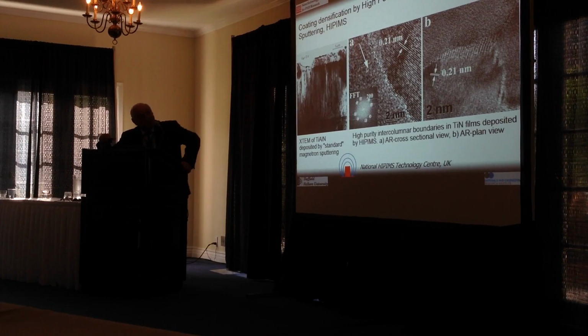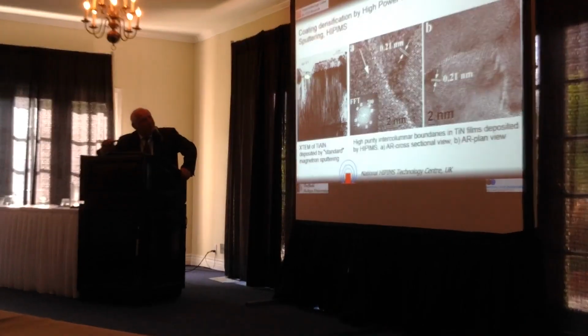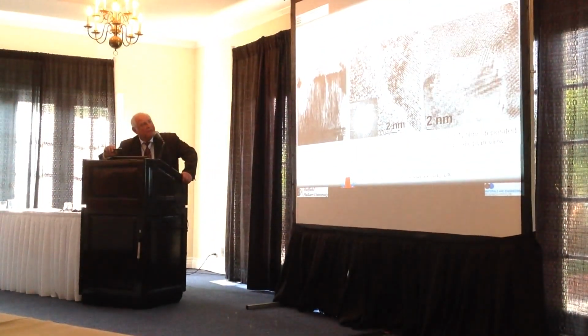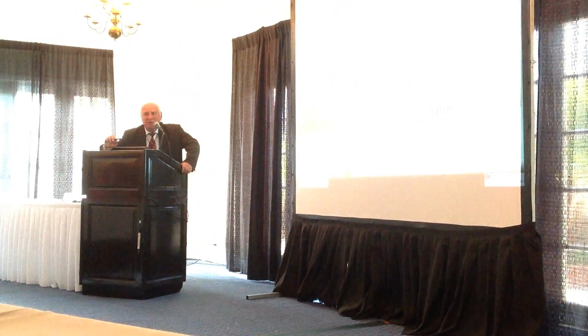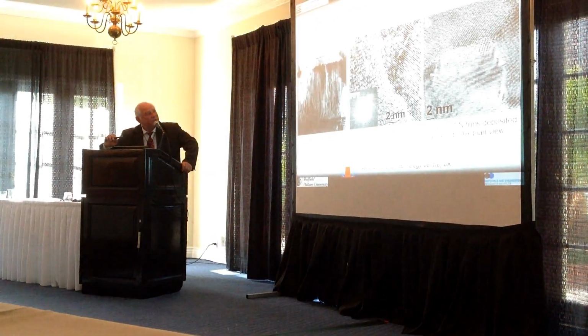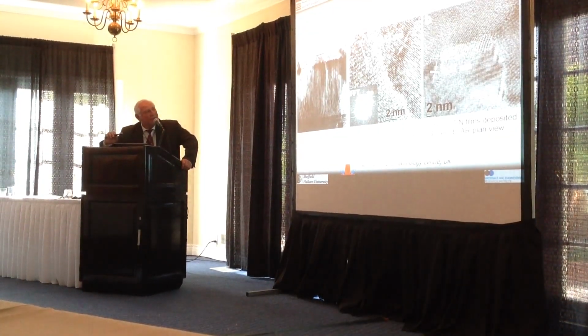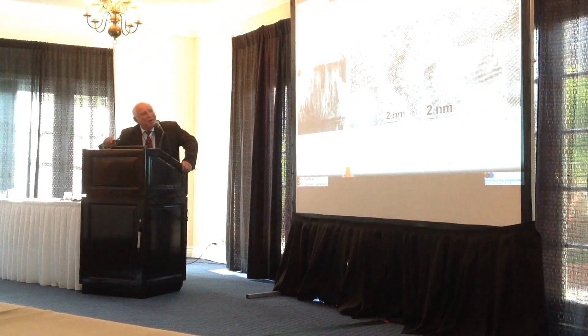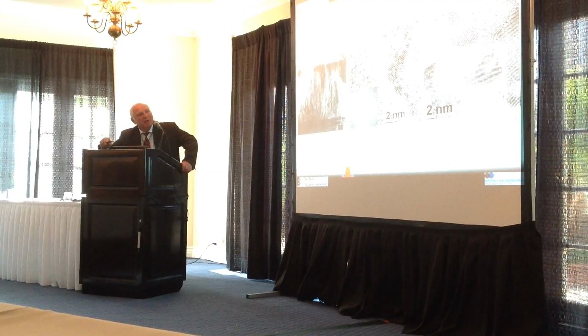Now, if you go further and investigate the coating density, this is just an example. Nobody is depositing in real life micron sputtered coating with zero bias. I used this picture just to show the danger of having open structures and to contrast it to what we see with HIPIMS. This is a plan view. You make a cross section like this and observe from the top.